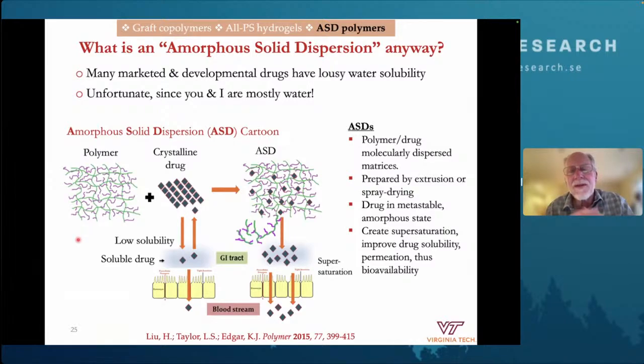The pipelines of pharmaceutical companies these days are turning out very hydrophobic drugs, and people like me, organic chemists, get tasked with making 100 analogs of that promising drug lead. We make 100 analogs, and we love to make crystalline analogs because they're easy to purify, and organic chemists love to crystallize stuff. What that generates is 100 analogs, all quite hydrophobic because they bind tightly to hydrophobic pockets on protein targets, and also crystalline. So they've got two strikes against them with regard to water solubility. Sure enough, roughly 90% of the candidates coming out of pharmaceutical companies these days have poor water solubility, and you and I are mostly water, so that's a problem.